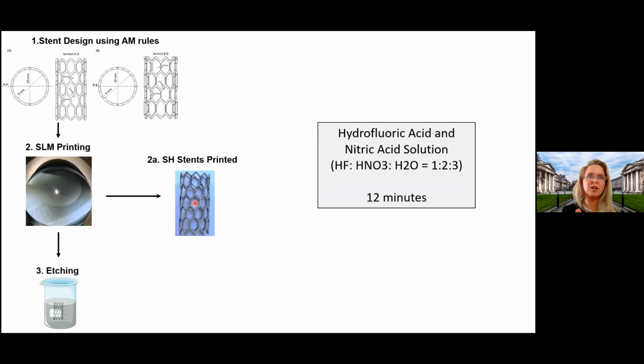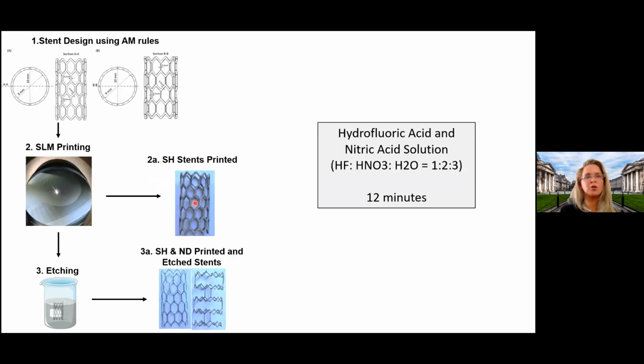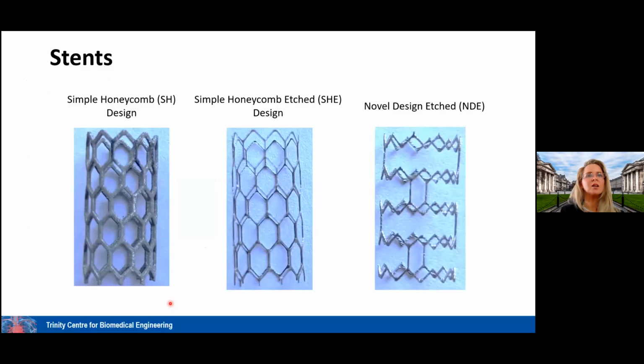So we're going to use the etching to bring that down, get a better surface finish, but also to give us more flexibility in design, to enable us to remove supports that otherwise, if you tried to cut those supports away, you would break the stent. So you can't really do that. This etching procedure is a way that we can do it effectively, or at least we hope. And I will show you here how we achieve that. I suppose we have two approaches here. We etch away to thin the struts and we etch away to remove supports. And we have two different etching times for these to achieve those, and you'll see that has a big impact on the performance of the stents.